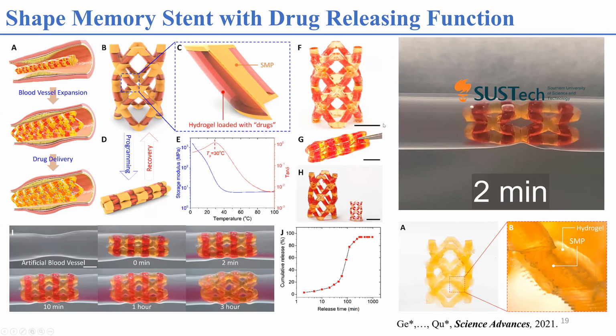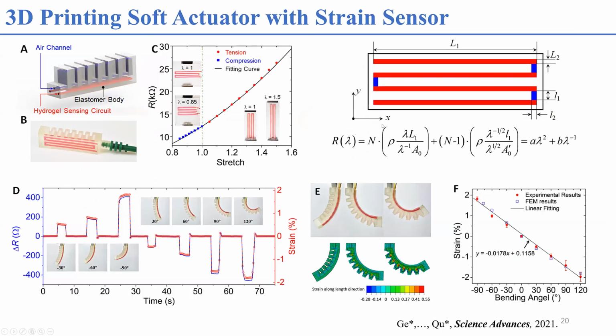And also hydrogel, if you add salt into the hydrogel, becomes electroconductive, and then if we do the printing, we can print a hydrogel circuit. And if we print the hydrogel circuit onto an actuator, we can make the actuator able to sense the deformation. When we apply air, the actuator bends, and we will find that the resistance changes, and then we will know how much the actuator bends.